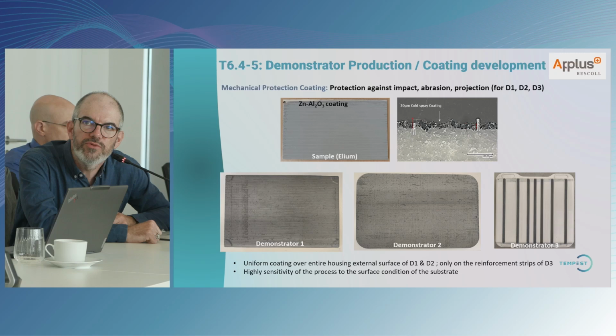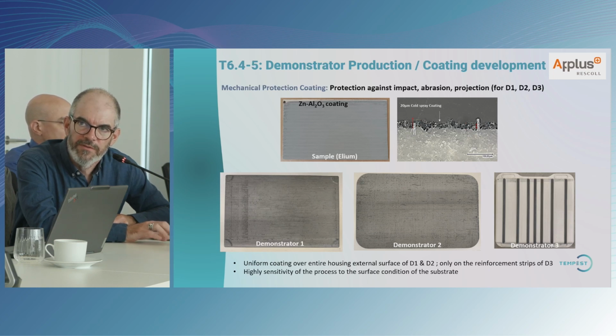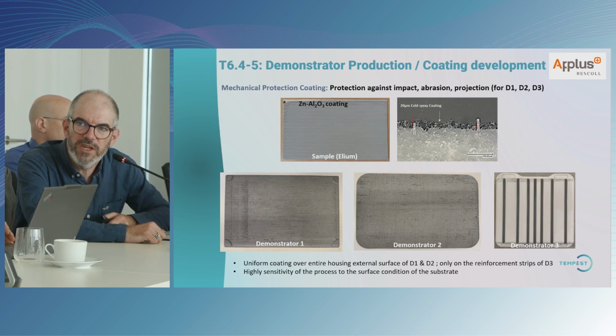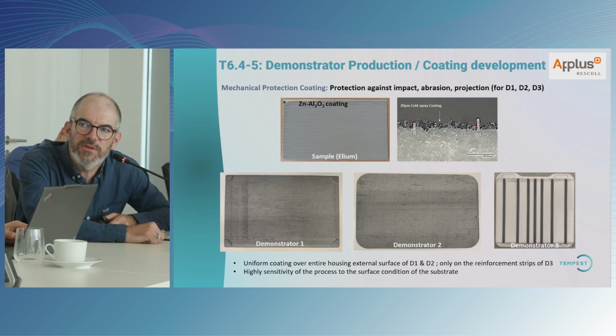And we were able to do different nice things. For the mechanical protection coating, we tested the coating on the different demonstrators. First on the coupon, on sample helium plates, it went well. And then on demonstrators 1 and 2, D1 and D2, we got nice results, uniform coatings, but demonstrator 3 was more challenging, and in the end, my colleagues were able to have a nice coating only on the reinforcement.